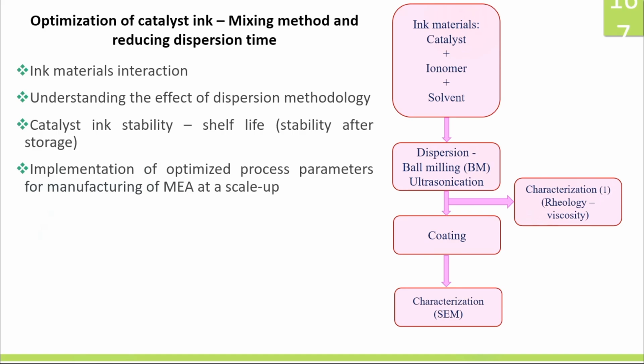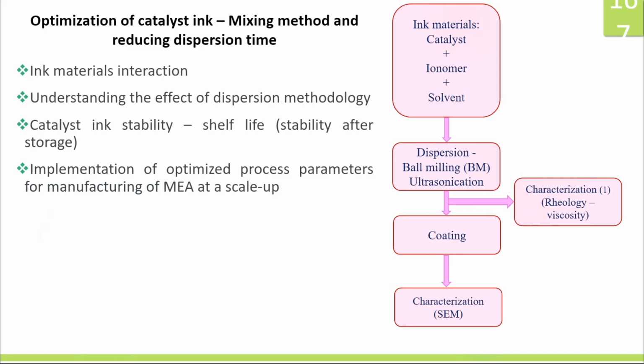So it shows that, for example, if we want to run the fuel cell stack or electrolyzer stack, we need to have a proper catalyst and proper ionomer. I will tell you why. If we have a long side chain ionomer, it means that we have less sulfonic group compared to the carbon and fluorine that we have inside. It means that when we are making ink, we have less water retention. Now imagine that we are building a stack and we want to run that stack in fully humidified condition. In that case, we cannot use long side chain ionomer because we end up flooding soon inside the MEA. But if we want to run a stack in dry condition, then our option is shorter side chain.